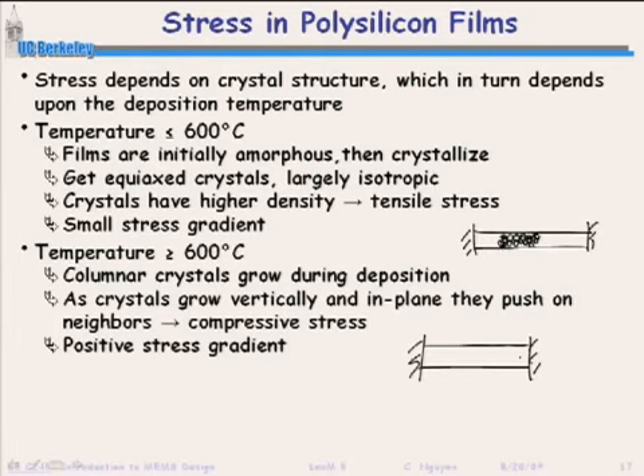They go all the way through the thickness of your film. And so what happens when they go all the way through the thickness of the film? Well, they have some ruggedness, and so they don't exactly line up. So they have this space between them, which means in the end, it wants to get bigger than your substrate does. So this is how compressive stress happens. So usually, you get tensile stress with low temperature, and you get compressive stress with high temperature.